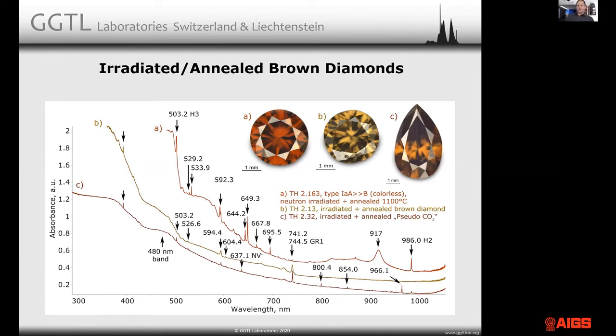So if you treat a brown diamond by irradiation and then start annealing it, this one has been annealed only to, I think, 800 degrees, if I'm not wrong. Then the defects you need in order to create a more attractive, or a different color than brown, will not be formed. So in this case, we have created barely anything that will change the color from the continuum. If you want to change the color of a brown diamond, you need to create other defects strong enough on top of the continuum that the color will change. And this didn't happen here.